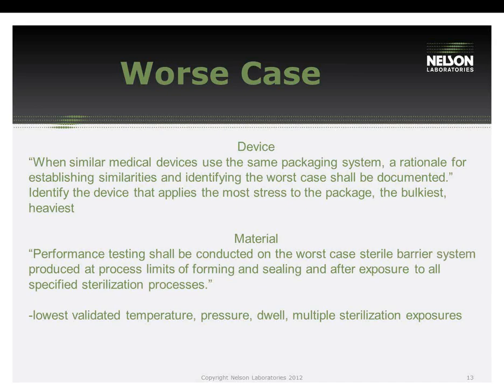And what this means is to pick the device that applies the most stress to the package. Is it the bulkiest? Is it the heaviest? Those are some of the ideas behind establishing a worst case device. When you're looking at material, it includes whether it goes through different temperatures, pressure, dwell, or sterilization cycles. The performance testing shall be conducted on the worst case sterile barrier system, at the process limits of forming and sealing, and after exposure to all specified sterilization processes.